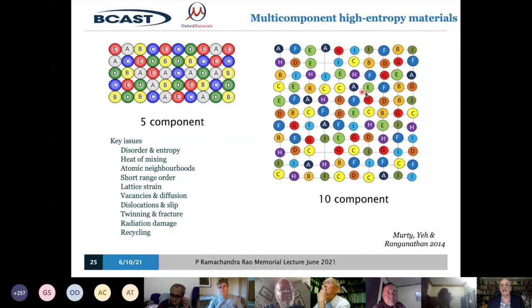In the Cantor alloy, or in any of the multi-component alloys, that's not true, of course, because there are more components. But it's a greater effect than that, because it's not just that there are 10 different components here. Take this A atom: it's got near neighbors B, F, C, and H, and second near neighbors E, C, F, and B. But if you take a different atom A, it's got different near neighbors and different second near neighbors. If you take another atom A, it's different again. So the local environments, there's lots and lots of them. I'll show you in a minute how many. It's an enormous number, it turns out to be.